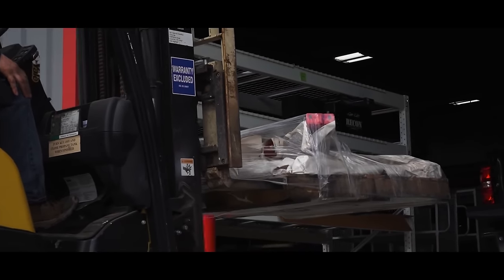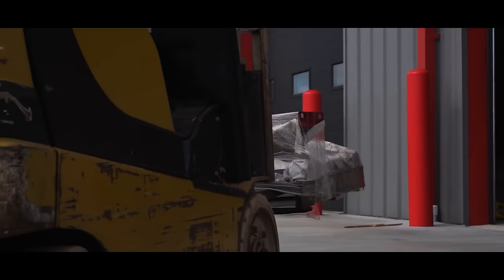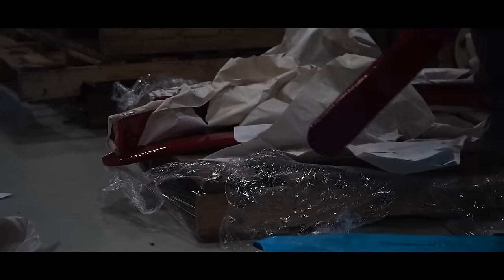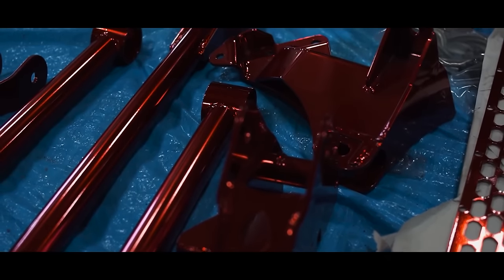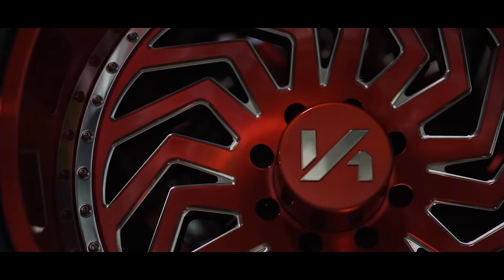When it comes to lift kits, that's another item that's really popular to get powder coated. The only downfall here is that because powder coat is so much more durable, it's also significantly thicker. So when you're prepping the kit, it's important to plug the holes and threads where your bolts are going to go in — because if those get powder coated, you've changed the diameter of those holes for the bolt to go through, and you might need to drill them back out or the threads might need to be re-tapped because they're now full of powder.